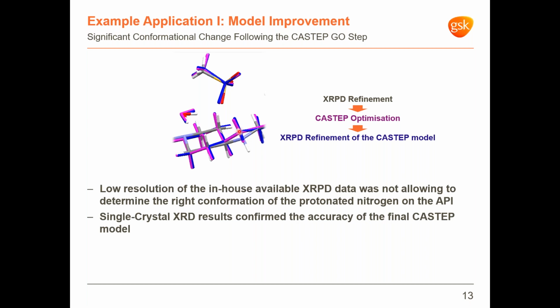So in conclusion, the low resolution of the in-house XRPD data was not allowing to correctly determine the conformation of the protonated nitrogen on the API cation, and eventually the single crystal structure, which could be determined later on, confirmed the accuracy of the final refined structural model.